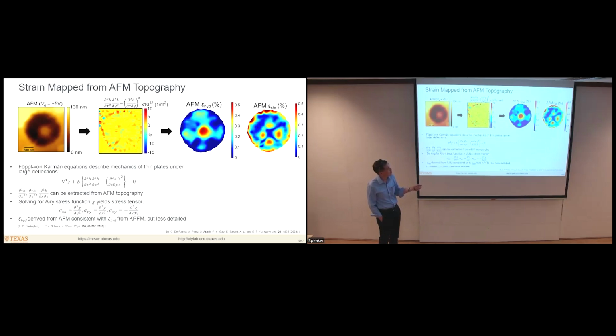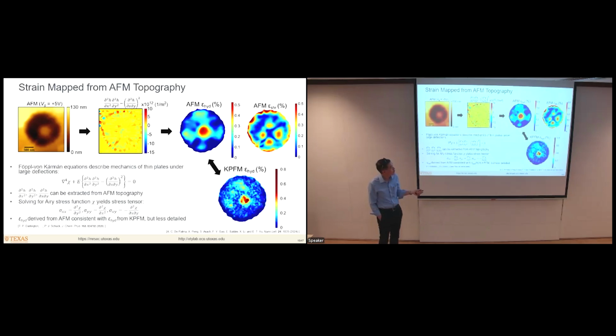This is the shear strain that you get using this approach. And if you compare that to what we measured using the Kelvin probe approach, then what you see is that the magnitude of the strain that you see is very similar, all right? Not only the central feature over here, but some of the peripheral features here and here, all right? But you see that there's much more fine scale structure to this than you get from the AFM-based approach, all